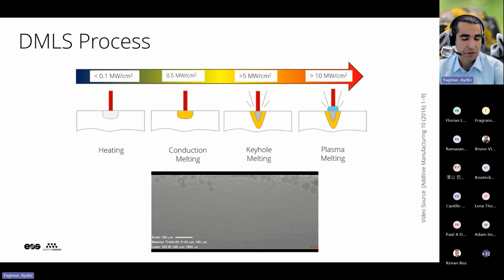If we go on increasing the power density further, we observe plasma melting, which is not desired for our technology because the created plasma interferes with the laser and prevents laser-material interaction, decreases the efficiency of laser absorption, and causes quality problems. So our technology relies on keyhole melting.